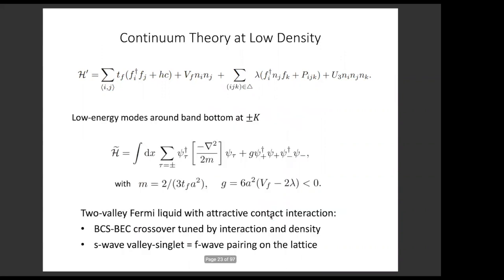So next slide. Of course, the mean field theory is only reliable when the effective interaction is somewhat small. However, there's another regime where the theory can be extended to stronger interaction strength, and this is the low density limit, where we can go to the continuum description. The doped electrons live at the bottom of the conduction band around the K and K prime points, and expanding the Hamiltonian around K and K prime gives rise to a 2-valley electron gas. Because it's a spinless system, the only interaction that is relevant in the RG sense is a contact interaction between the 2 valleys.